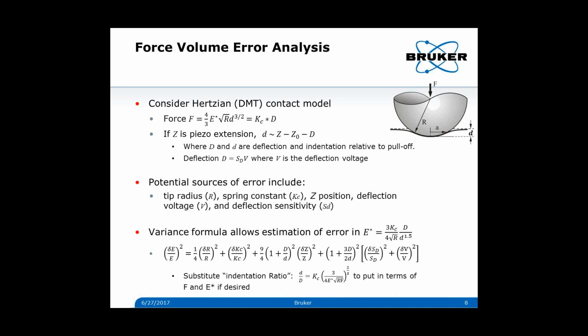So if you wanted to do an error analysis on this, we can estimate it using a simple variance formula. So let's just start out with a Hertzian or DMT contact model. Then we can calculate what the force is, and we can put it in terms of the deformation into the sample. The potential sources of error that we will consider are tip radius, spring constant, Z position, deflection voltage, and deflection sensitivity. And if you plug it all in, you get an equation that looks like this, where the first term is the uncertainty in the tip radius.